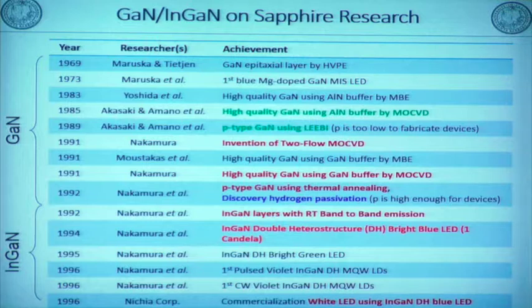In my case, the most important thing is '92: P-type gallium nitride using thermal annealing, and also the discovery of hydrogen passivation. This is the mechanism of P-type gallium nitride. Also in '92, indium gallium nitride. We got the first high-quality indium gallium nitride, which showed band-edge emission, in '92. In '94, we made the first high-efficiency blue LED using the indium gallium nitride double structures. Also green LEDs in '95. Also, we got the first laser diode, a violet laser, in '96, with CW operation.